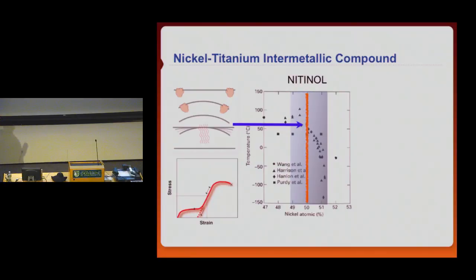So if you take an alloy from this composition, say a little titanium rich, you get shape memory because now you have a transformation temperature that is above room temperature, and if you do a tensile test with this alloy, you get a tensile curve that looks like this one. You have a first elastic range here, and then you get something that we call a stress plateau, where you get a significant amount of strain without increasing stress. And then at this point, you get a second conventionally elastic range and then plastic deformation. Now when you unload, the unloading follows this curve, and it does not get back to the starting point.